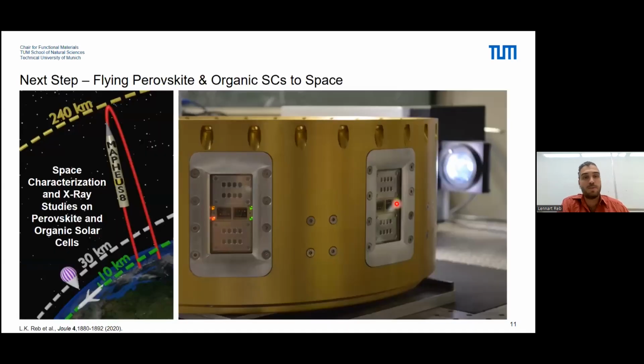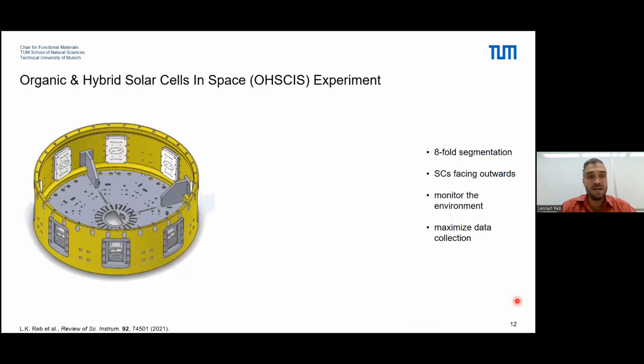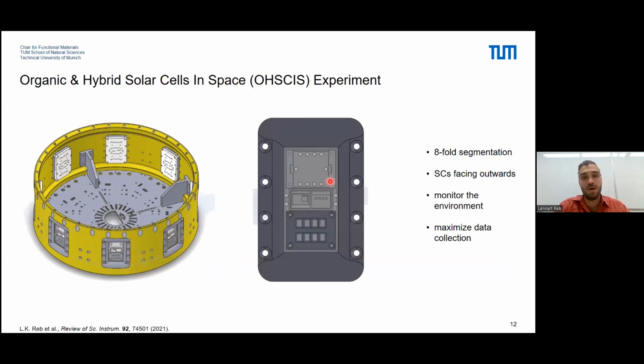And this brings me to the next step, which I call here flying perovskite and organic solar cells to space. Here on the left, you can see what such a suborbital rocket flight trajectory looks like. And here on the right, this is the experiment that we used in our labs during testing with the solar simulator. This was our CAD sketch of the experiment, a round ring with 8-fold segmentation, with 8 windows where the solar cells are placed. We also wanted to monitor the environment to maximize data collection. One of these windows has one spot for a solar cell on top and a second one on the bottom, and in between we have some sensors.